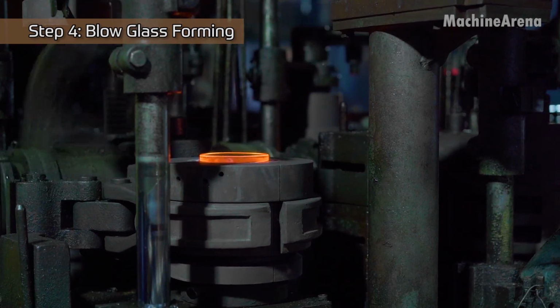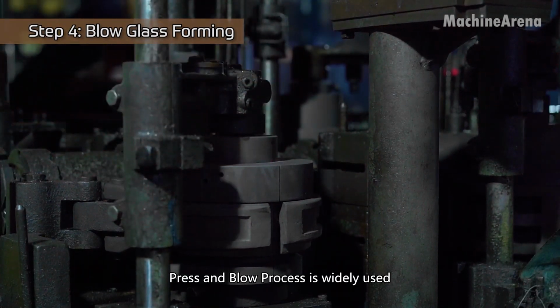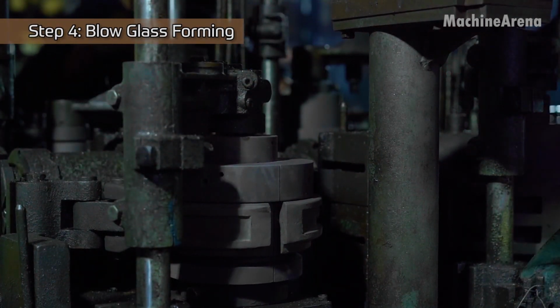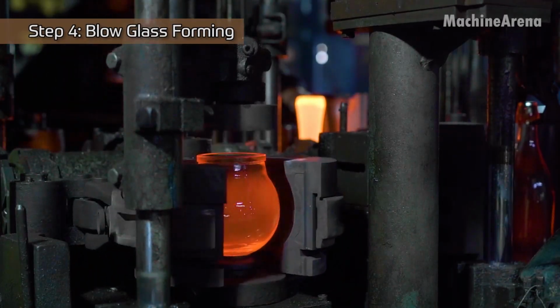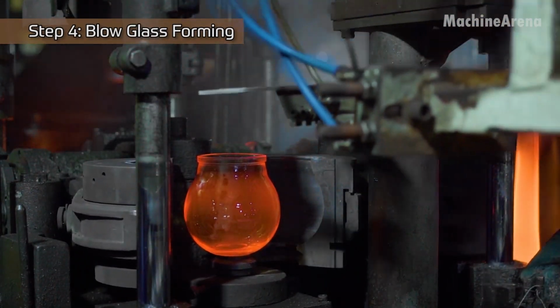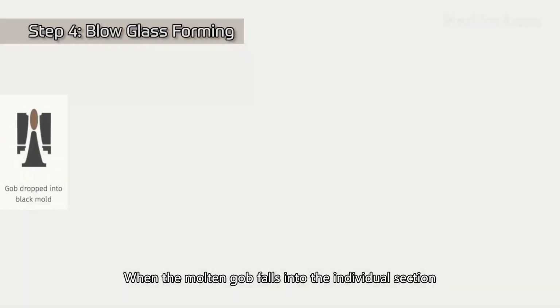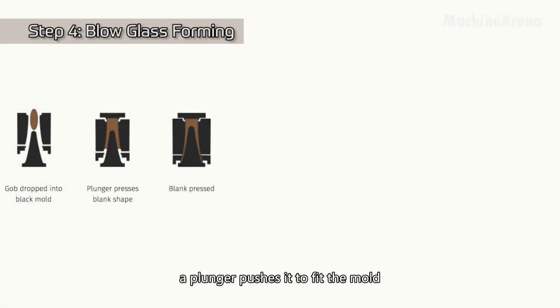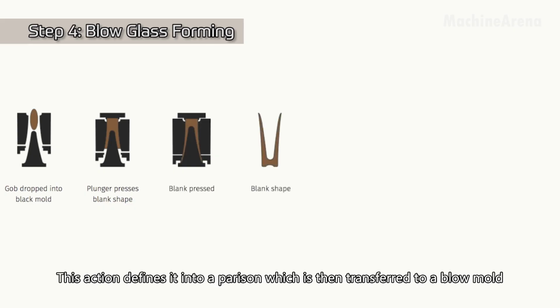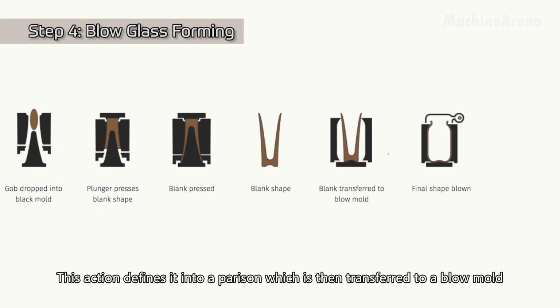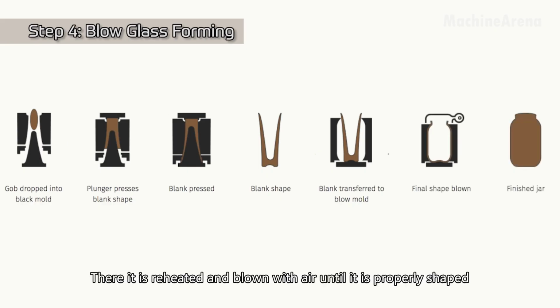Two main techniques are used: blow and blow, and press and blow. In the blow and blow method, a puff of air forms a cavity inside the gob, followed by a second blast that expands it to fill the final mold. In the press and blow method, a plunger first pushes the glass into shape before air is used to refine it. The choice of method depends on the desired thickness and shape of the bottle.